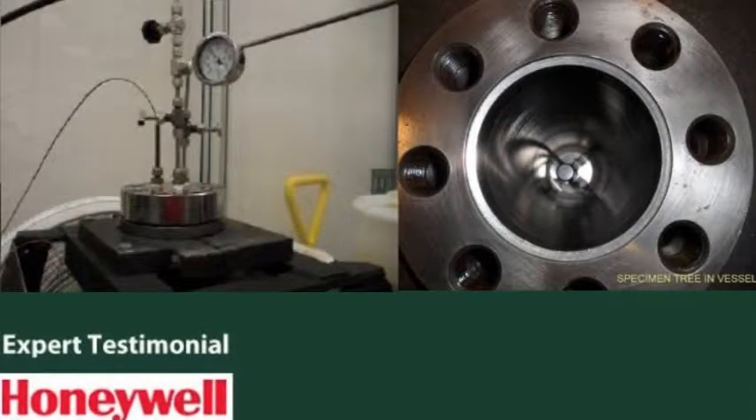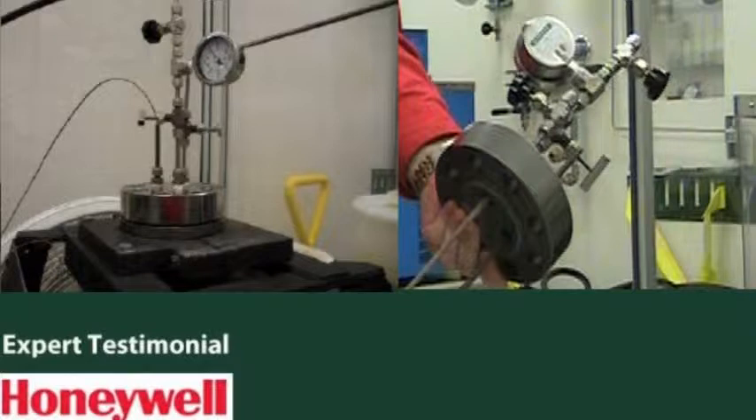The Tantaline process we were interested in was treating a single autoclave to give us the corrosion resistance needed for these rather extreme acidizing tests. We took a 316L stainless steel 2-liter autoclave — I think it's 3-inch inner diameter with about a 17-inch depth — so not a trivial autoclave, along with all of the associated parts: typical pressure line parts, purge tubes, valves, connections, the thermal well, and also coupon holders. These are stainless steel rods with all-thread — threaded parts, the nuts that go on those all-threads — basically everything we need to suspend corrosion test coupons in the solution and plumb up the autoclave in terms of pressure integrity and environmental control.